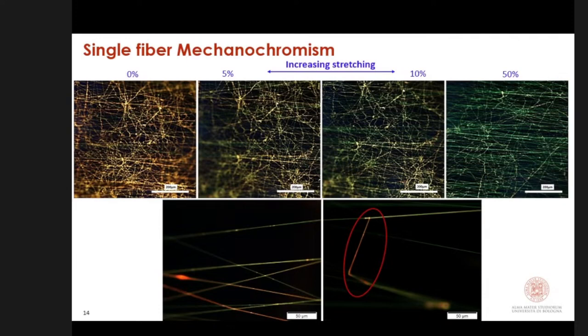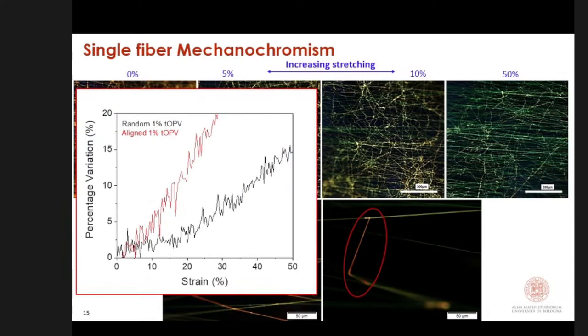And this is the explanation for why we obtain these two very different responses with the two different morphologies, because only in the aligned mat do we have all the fibers oriented in the same direction of the applied force, while in the random mat only a part of the fibers are oriented in the right direction.